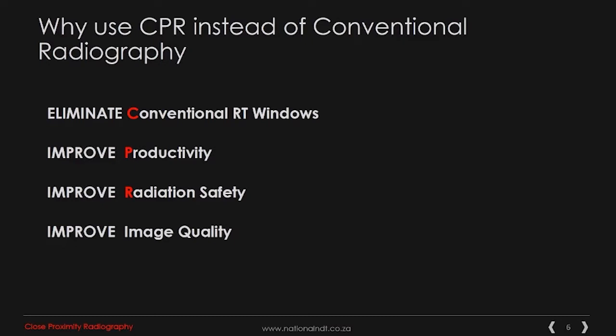It would allow for the improvement of productivity and radiation safety, both for members of the public as well as for radiation workers themselves. With the utilization of selenium as opposed to iridium sources, we have an improvement in image quality, simply because selenium in terms of an isotope is closer in wavelength to x-ray than it is to iridium.